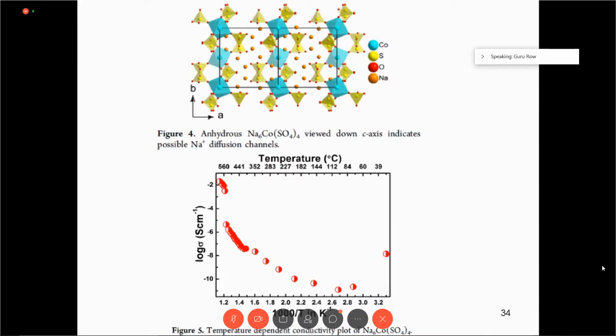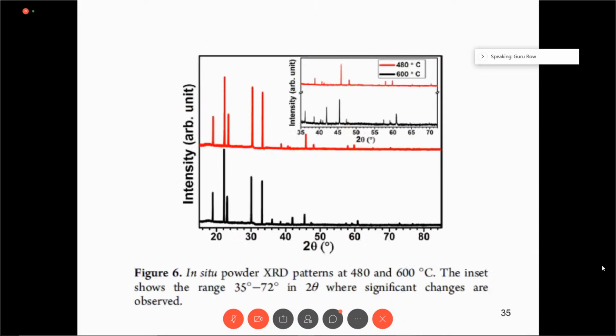This has been also followed by Raman studies and also from in situ powder diffraction. We have done the in situ powder X-ray patterns at 480 degrees and 600 degrees. The essential changes in the structure are observed here. So the structural changes essentially facilitate the superionic conduction in these materials.